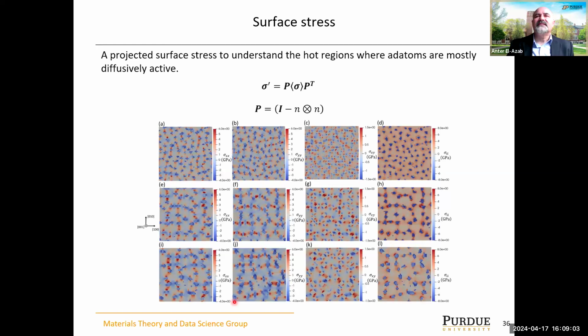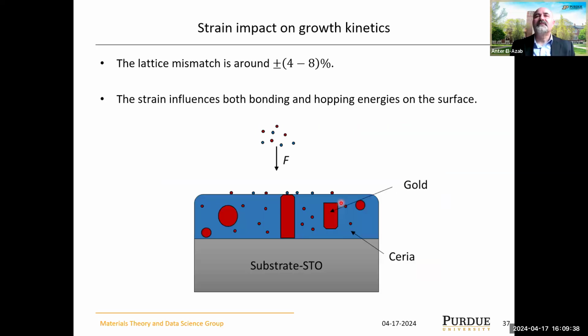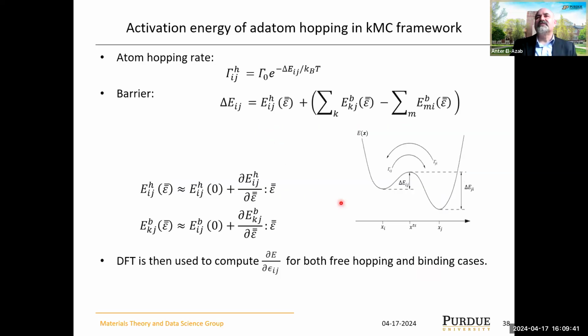So that's what you see in the map. It's projected here. That is a part of the strain field that will interact with the diffusing atoms. The atoms that deposit on the surface will see this kind of strain on the surface, and the strain, being a local quantity now on the surface, will alter the hopping energy and the bonding energy depending on the magnitude of the strain at various locations here. So we're expecting to see a significant effect of this if the coupling between the strain and the hopping and bonding energies is significant. So back to the parameterization again.